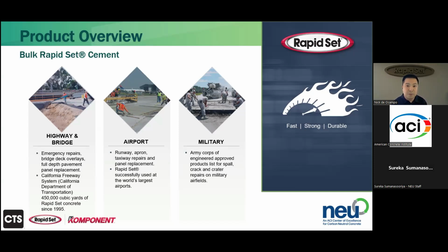A third application would be military. The Army Corps of Engineers has approved several custom bagged and box mix designs, bulk and bag mix designs, repairing critical military infrastructure. This is especially important for repairing cracks and craters on military airfields. In the case of damage or explosive attacks, if there's airfields near enemy lines, these mixes are designed so that any GI unit can come in, place the CSA cement repair material, and have a damaged runway back up and running to allow aircraft to take off to provide support, and perhaps more importantly, to get planes that may already be in the air landed and back safe on the ground.